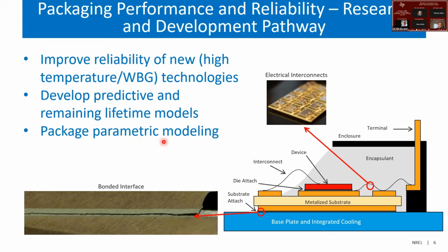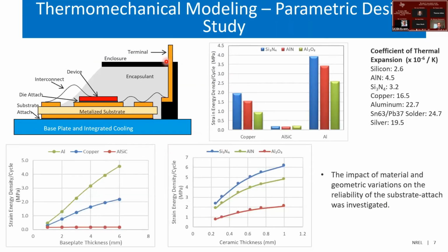With package parametric modeling, we work with numerous industry and research colleagues, helping guide the design and development of advanced module, package, inverter, and converter configurations. Maybe that's one example I'll give, taking this cross-section as an example. We compute strain energy density within this substrate attached layer, and focusing on this graph, strain energy density for different base plate materials: copper, AlSiC, and aluminum. And then we have, of course, the 3 different ceramic materials. Low strain energy density per cycle is an indicator of better reliability. We have seen that experimentally.